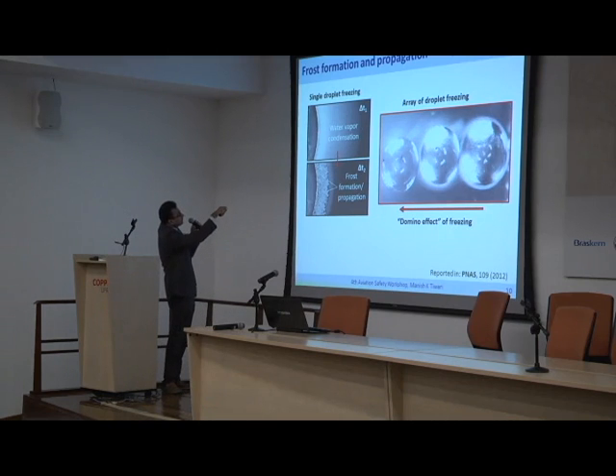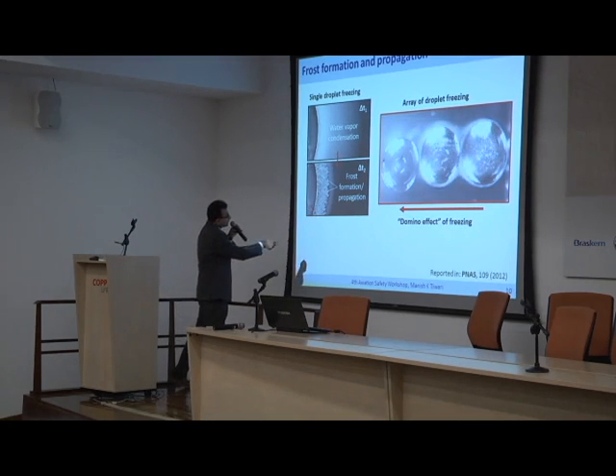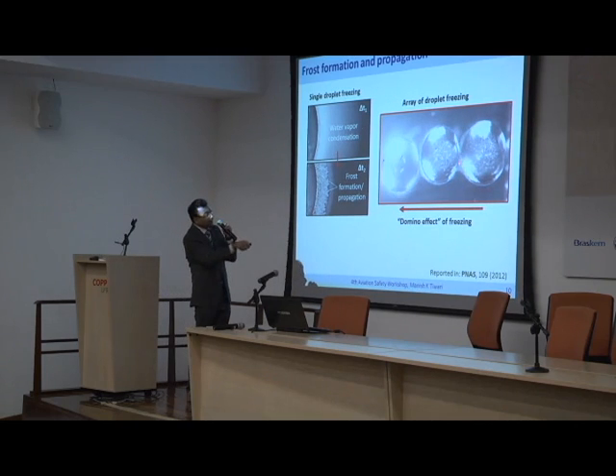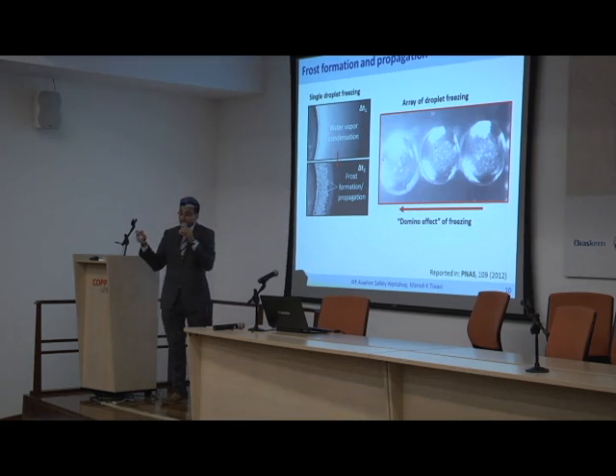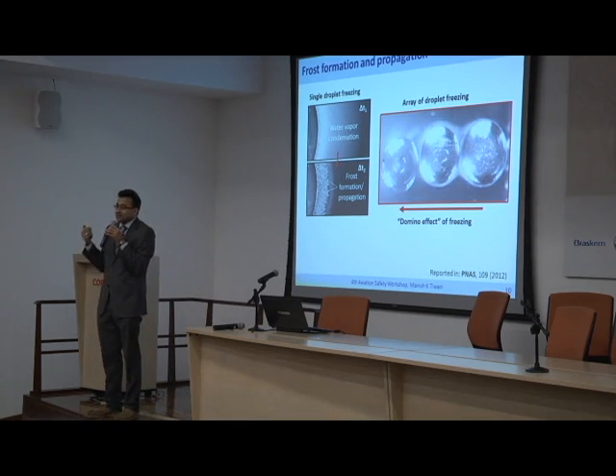If you don't believe me, here. This is the part of the original droplet under the microscope, and this is a bright field developed around this original droplet. And you see condensate formation. Now some of this condensate touches the original droplet and forms a frozen ring around the original droplet. Now that frozen ring can touch the next guy, and so on and so forth. So the message here is, if we are trying to make an ice-phobic surface, let's not make them insulators.